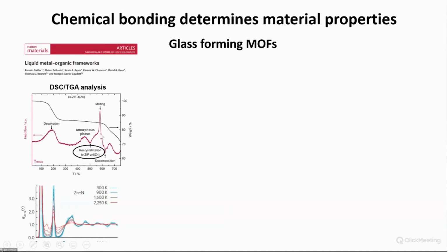And then this structure melts. And then if you cool that, you have a glass. So this famous, I think really in this field, very important study showed that as you heat it up in the melt, basically the structure is preserved. And this is the 1D PDF that shows the chemical bonding preserved.